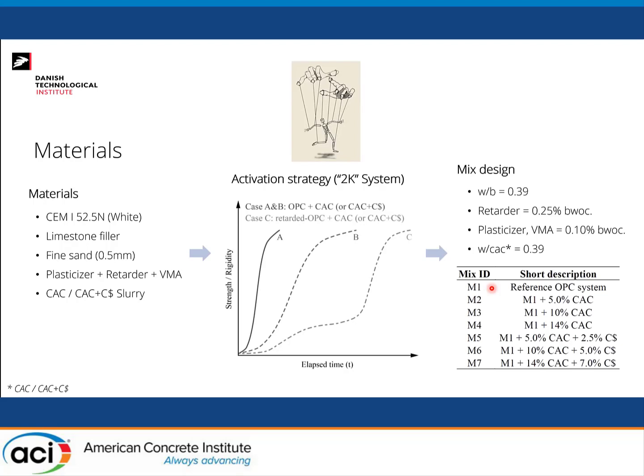And then in terms of mix design, these materials were combined based on the numbers you see on the screen. Basically we have a water binder ratio of 0.39, and here I'm considering even the limestone filler as a binder, just so you're informed of that. The retarder dosage was fixed at 0.25% by weight of cement, and then the other two admixtures, plasticizer and VMA, at 0.1%. The CAC slurry, or calcium aluminate cement and calcium sulfate slurry, has the same water binder ratio as the initial mix, because the idea is that we don't want to disturb the initial rheological properties of the mix at the extrusion point. So there should be relatively zero effect at the injection point.